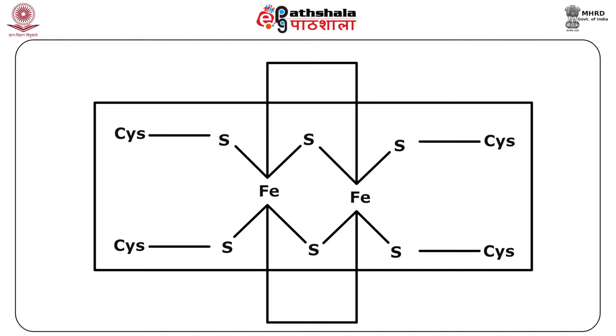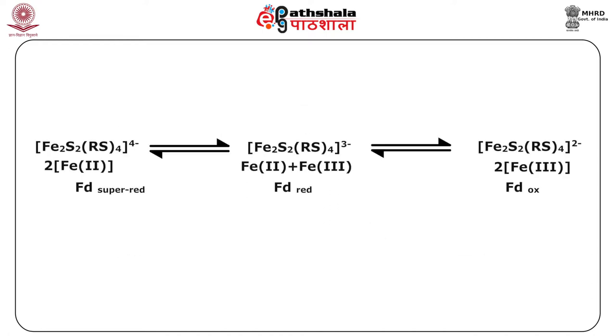This redox center is wrapped around the protein chain where the iron atom is coordinated to cysteinyl sulfurs. The cluster of the 2 iron 2 sulfur protein can be considered as bitetrahedral, where the iron atoms are bridged by the 2 sulfide groups and additionally bound to 2 sulfur atoms of the cysteine group per iron atom. The oxidized proteins bearing 2 high spin Fe3+ ions are diamagnetic at very low temperatures, while the reduced form is paramagnetic, corresponding to 1 electron.